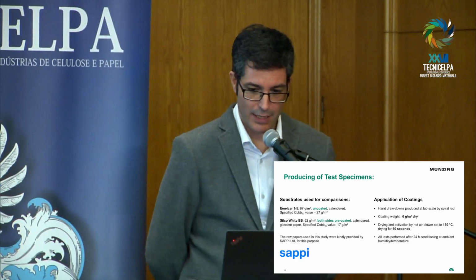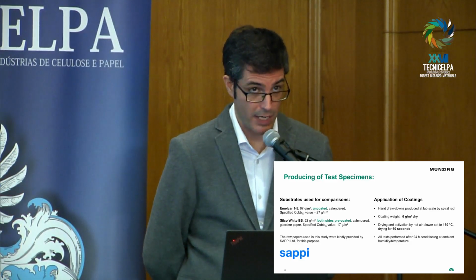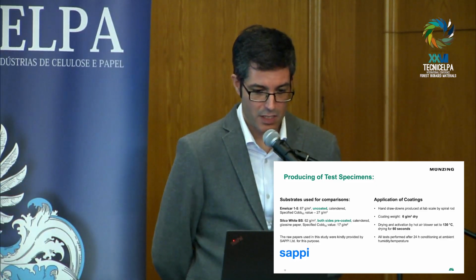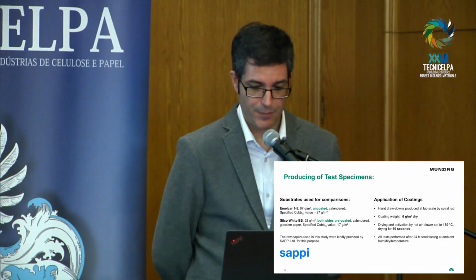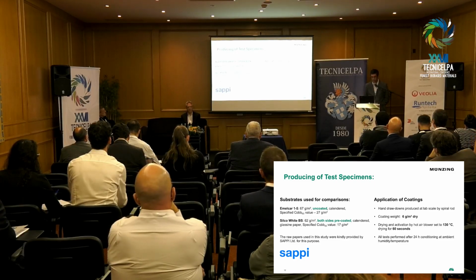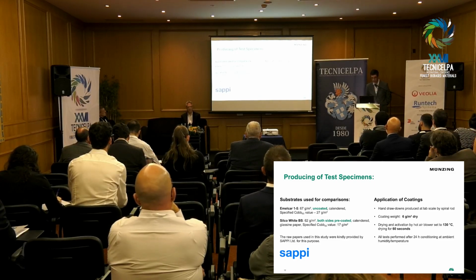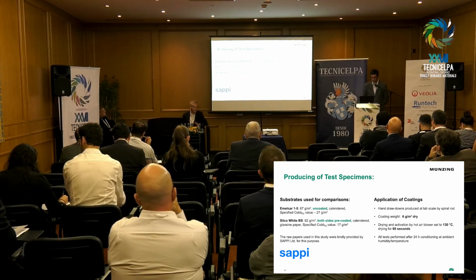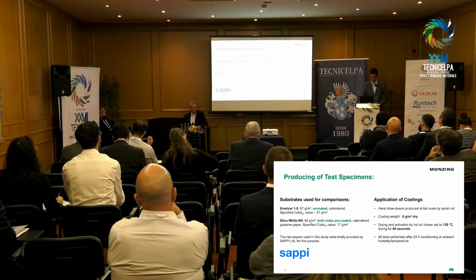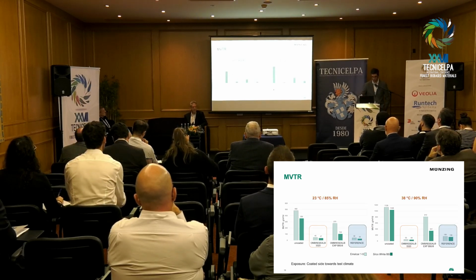The materials at lab scale have been applied by spiral rod. The coating weight is 6 grams per square meter dry, and it was dried and activated by applying a hot air blower at 130 degrees during 60 seconds. And we saw that this method is more realistic than putting the samples in the oven. That's why we did it in the lab in that way. Finally, the panels were conditioned during 24 hours at ambient humidity and temperature.